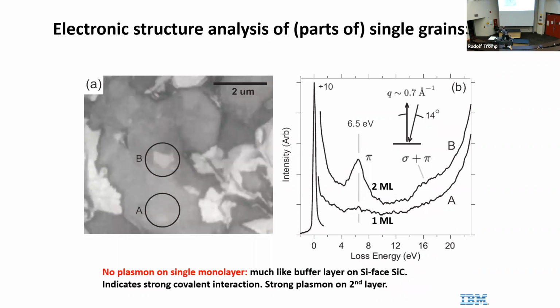You can then also place apertures here and here and record an electron energy loss spectrum. If you do it on one monolayer, this is the elastic peak. There's not much interesting going on here. When we go to the two monolayer part, we see there's a strong pi plasmon and a sigma plus pi plasmon. You might ask, well, why don't you see that from one monolayer of graphene?